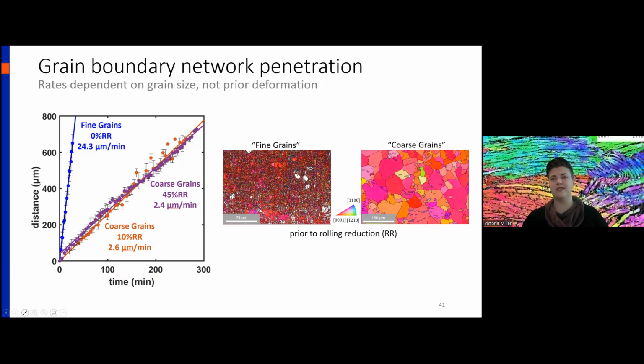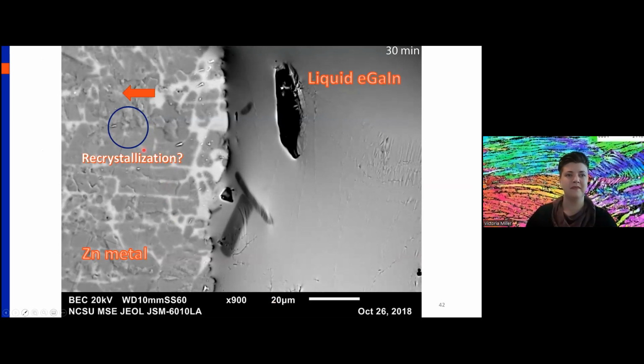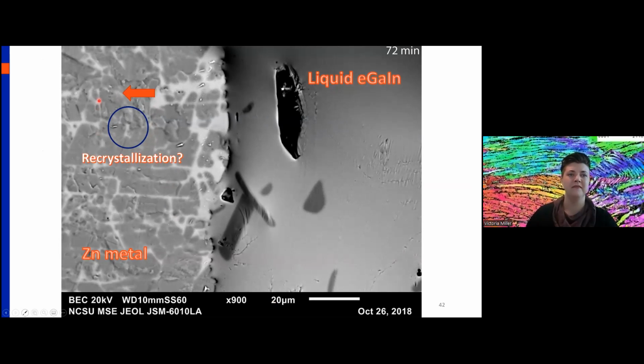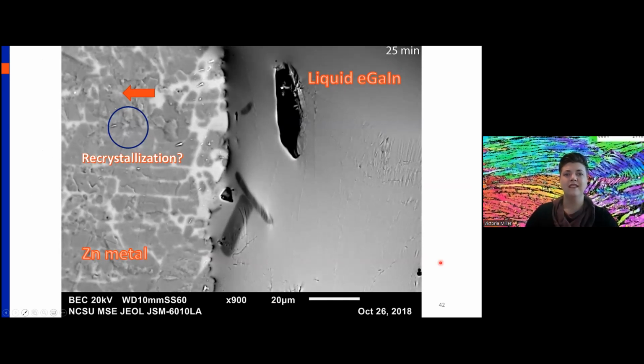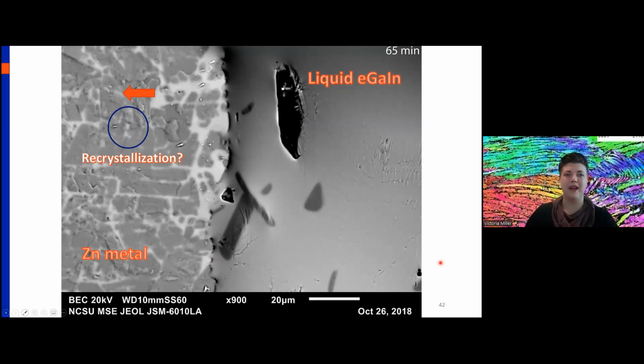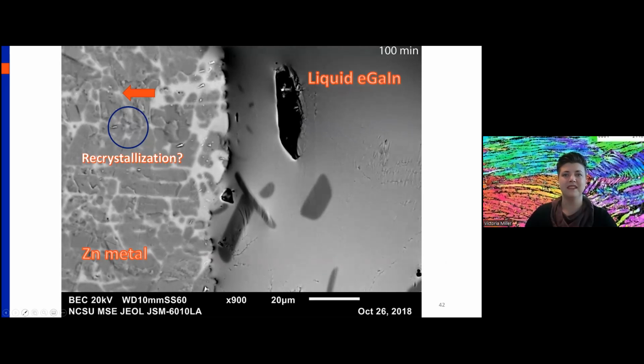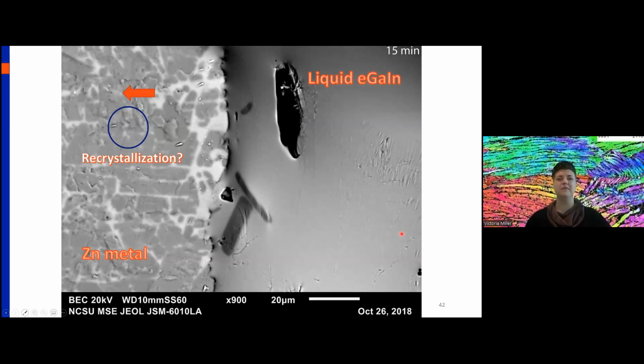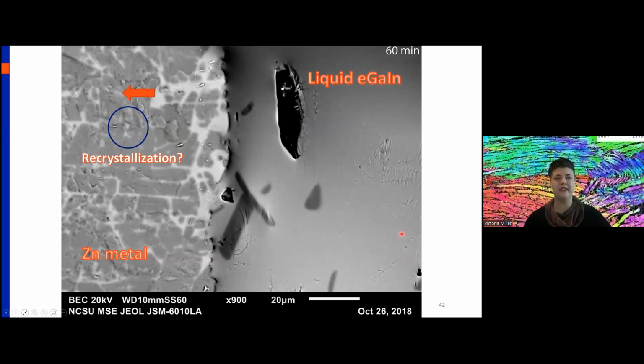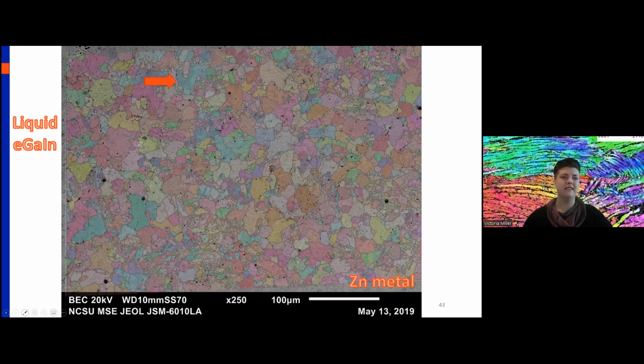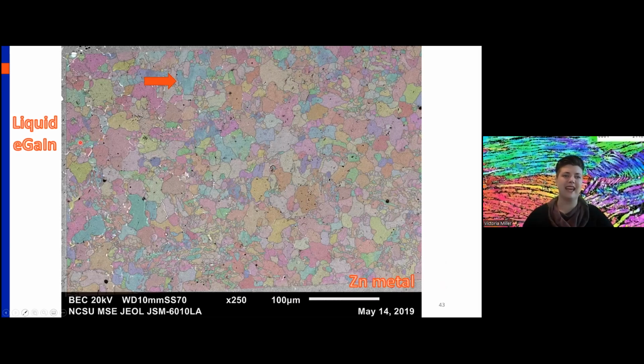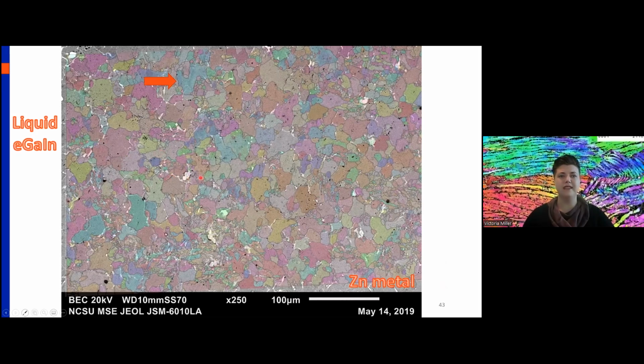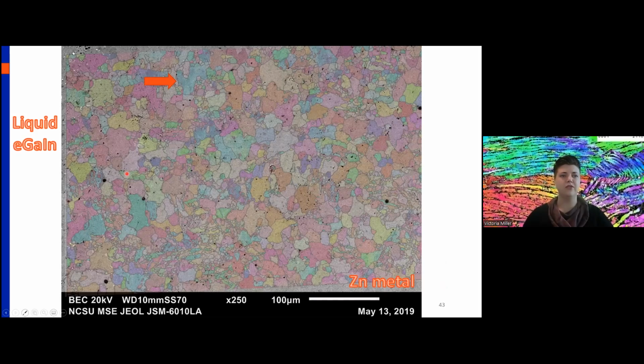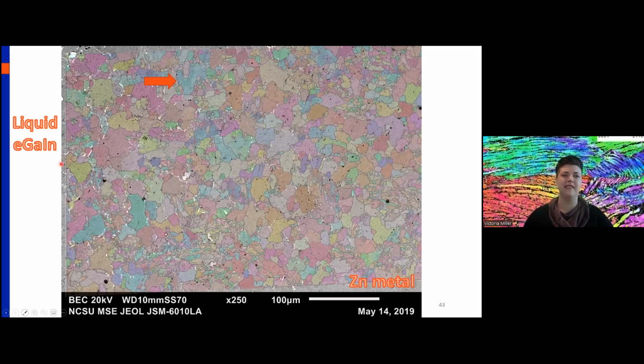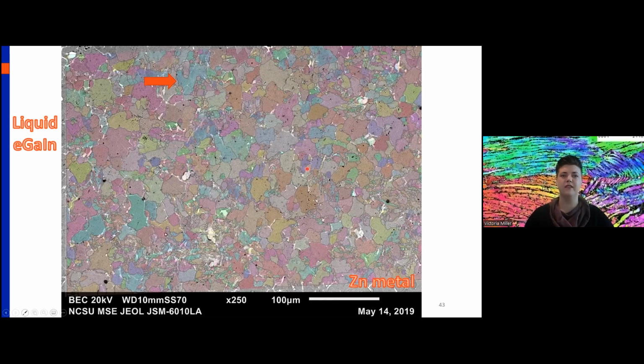When we were looking at some of these videos, though, we started seeing some really interesting behavior. If you focus on this circled area right here, it looks like you actually get the nucleation of a recrystallized grain mediated by the presence of liquid at the grain boundaries. So we wanted to look at this a little bit more clearly. We started by overlaying some electron backscatter diffraction with this GIF of grain boundary penetration. You can see the liquid eutectic gallium indium starts off here on the left, and it penetrates the grain boundary network to the right.